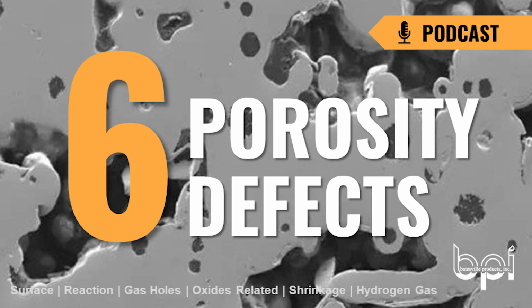I'll let Ernie go into detail because this is a very common problem, particularly on complicated or complex castings. First thing is it tends to be localized. Second thing, it's kind of misleading because you can machine across the surface with shrinkage porosity and it'll look clean, it'll look good, but it'll actually seep or leak because the interstices are all connected. So you may have a part that looks very good, but if you put it under pressure, you'll actually see it seeping a little bit.